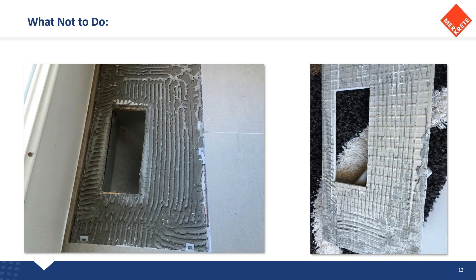Here's a job where they were complaining of cracked grout joints. I pulled one of the easier tiles to pull up — around the air vent register — and you can pretty much see what happened. If you look at what was left on the floor and on the tile, they really did not meet the required percentage of bond, which is 80% for interior applications. What was happening is they were getting movement in the tiles — they just couldn't withstand the impacts and vibrations over a wood subfloor — causing the tiles to be loose. The tiles weren't cracked — it was the grout joints that cracked.